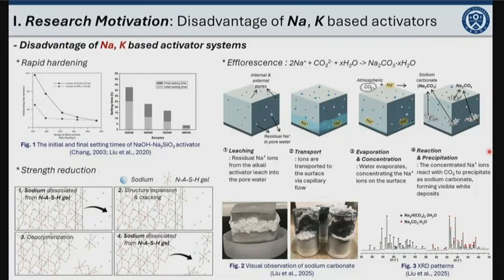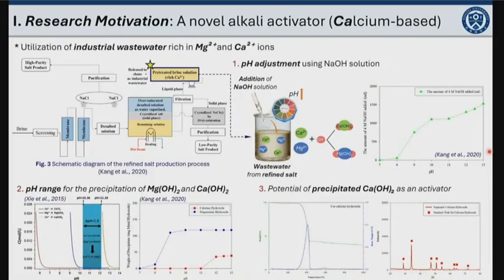The sodium ions also tend to leach continuously from the relatively weak N-A-S-H gel, which not only reduces the long-term strength, but also leads to efflorescence. As a solution to these limitations, calcium-based alkali activator was recently proposed. Since the calcium-based activator is similar to the early hydration product of ordinary cement, it can effectively prevent rapid setting. In addition, this can promote the formation of C-A-S-H gel, which exhibits stronger bonding than the N-A-S-H gel, thereby mitigating the long-term strength reduction and suppressing efflorescence.